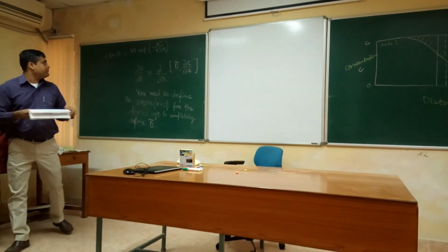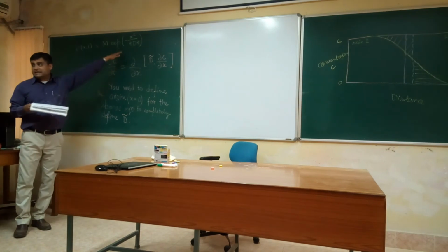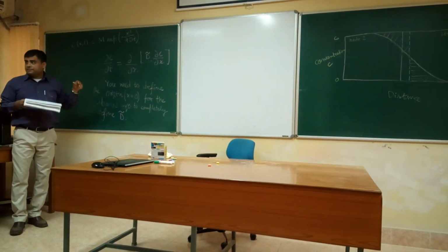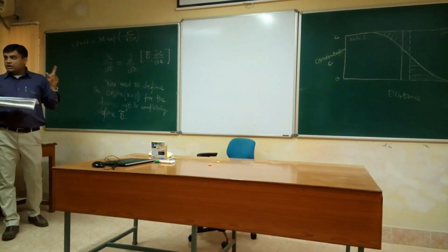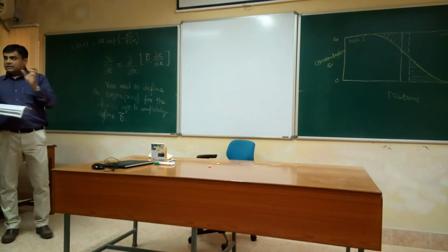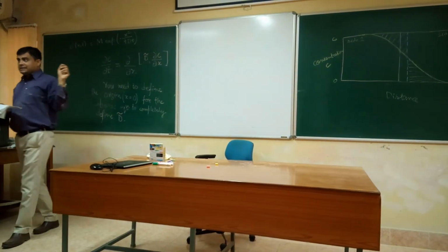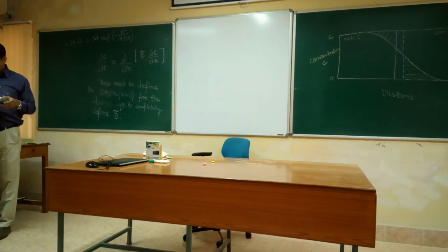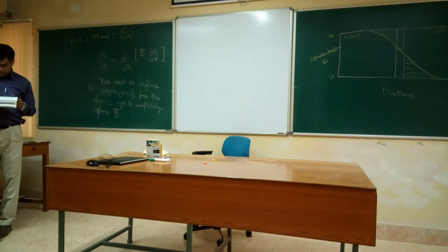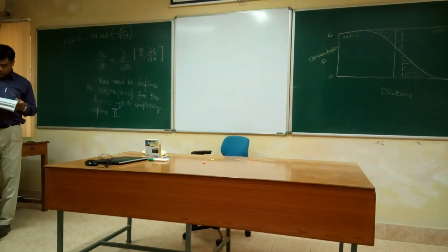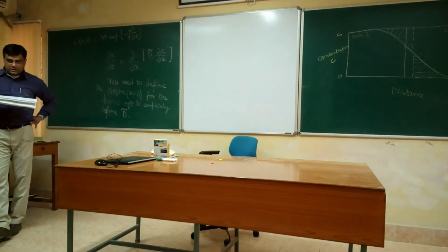So a graph of ln C versus x squared will be linear, because for a specimen your annealing time is fixed. So from the slope you can get D, the self-diffusion coefficient.